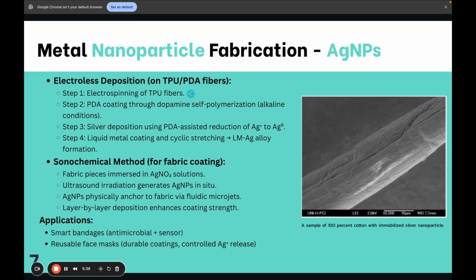We use TPU fibers because they are flexible, durable, and biocompatible, and are also perfect for wearables or biomedical use. Then comes PDA coating via dopamine self-polymerization. The TPU mat is dipped into dopamine solution and undergoes oxidative self-polymerization, forming polydopamine on the fiber surface. Now, why do we use polydopamine? We use polydopamine because it has catechol and amine groups, and it reduces metal ions to metal atoms.